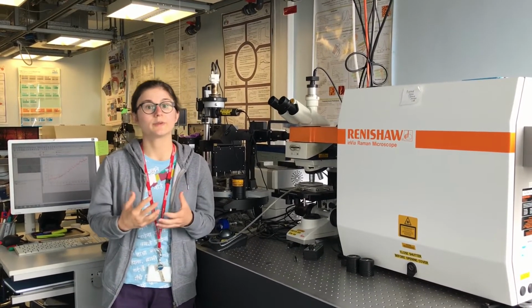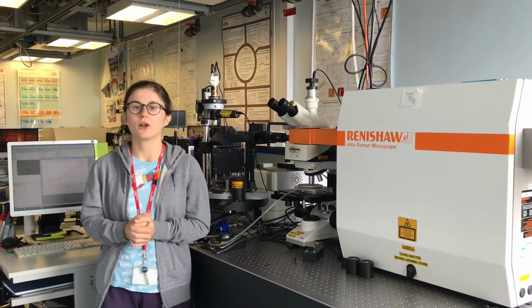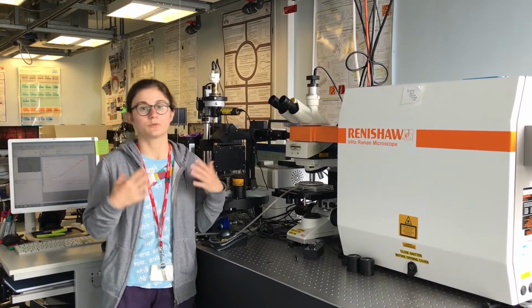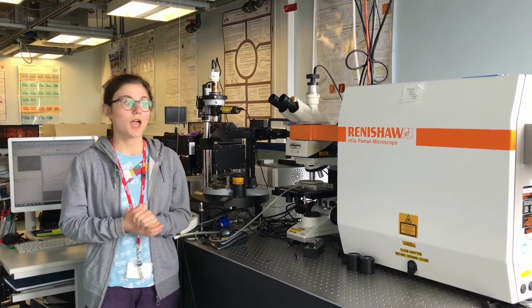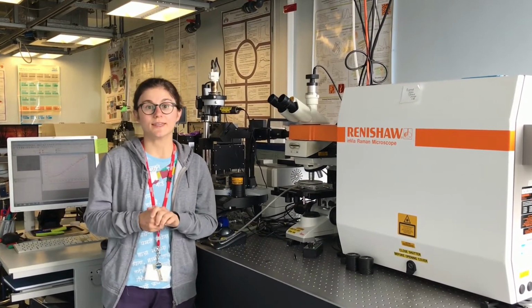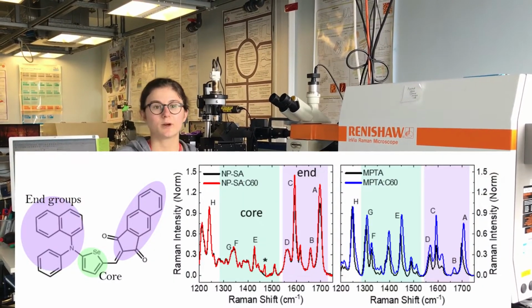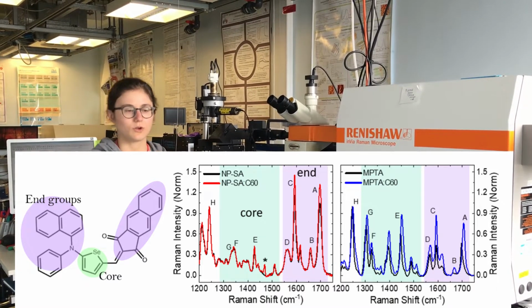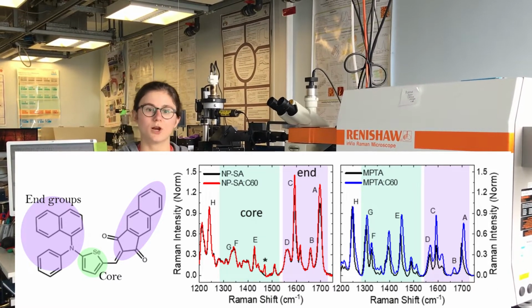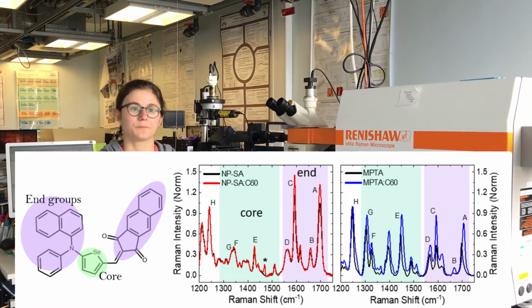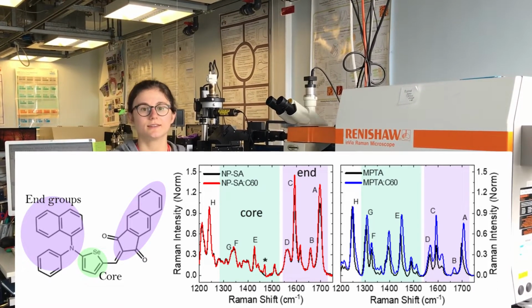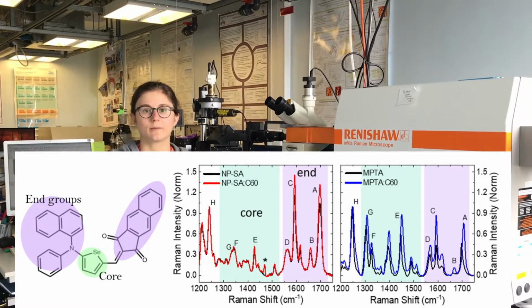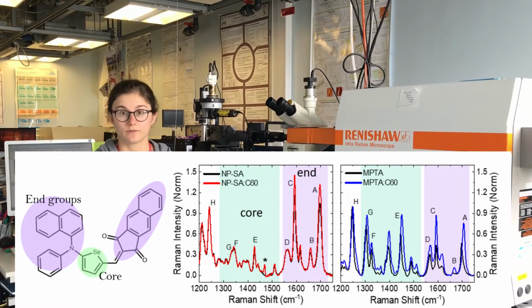To confirm this very peculiar morphology, we can use the Raman spectrum, of course, for investigating the vibrational modes of the molecules. We can see that the effect of blending for the twisted molecule is very localized, just on specific modes, but for the planar molecule it is very general, so all the modes are affected by the blending. So again, we think this is compatible with some stronger organization of the morphology.